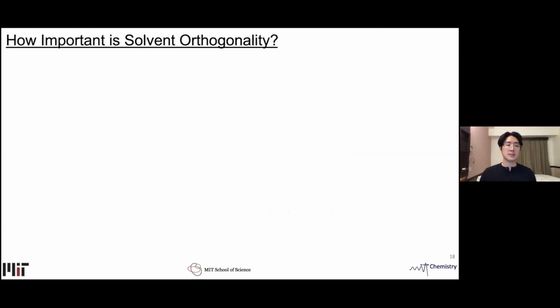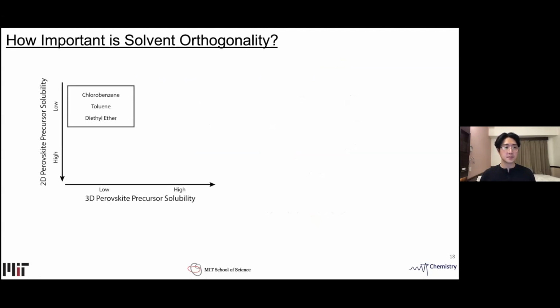Now, with the device fabrication being done in a solution processing manner, we decided to understand the effect of solvent orthogonality on the passivation. On the left, I'm showing the solubility of the 3D perovskite precursor and the 2D perovskite precursor, going from low to high.